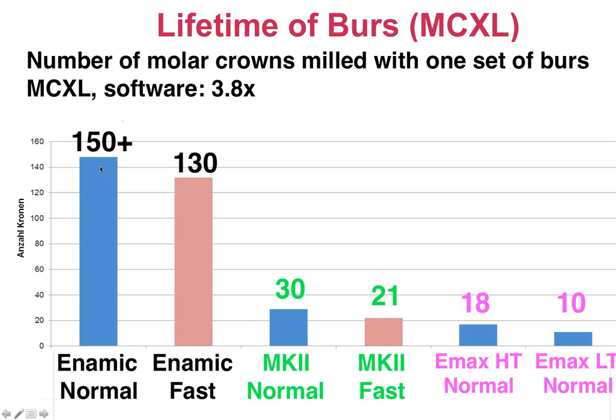But in this case, it was the end of the day, and they got to 150 blocks for the normal mode on the MCXL, and they stopped. They did it in fast mode as well. This is 130 blocks for one set of burrs. I know in the clinic we have a variety of milling machines.